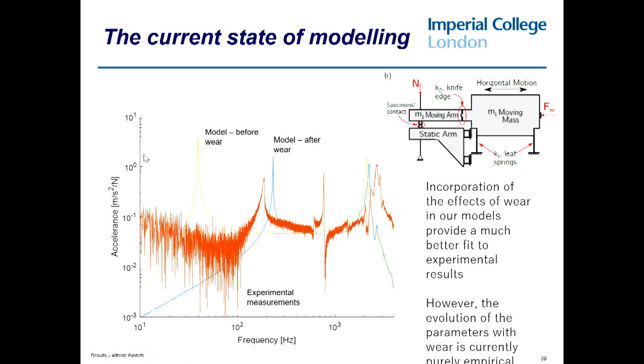And if we model this system, we get this yellow curve here. If, on the other hand, we take account of how the system wears and how that changes what's going on at the interface, we get this blue model here, and that ties up much better with our experimental measurements of the system response. So seeing how the interface develops is as important as seeing what the interface looks like when it's new.